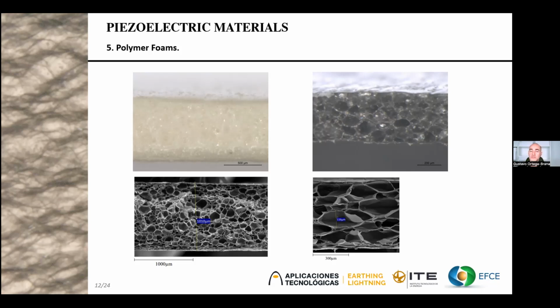On the left, we can see the polypropylene polymer foam that has a thickness of 1 millimeter and closed cells, of course. Below, we can see the cellular structure taken by an electron microscope. In the case of the polypropylene samples, the ratio of air and polymer is approximately 88%, and we use a density of 100 kilos per cubic meter.